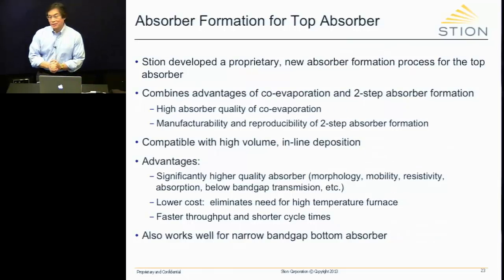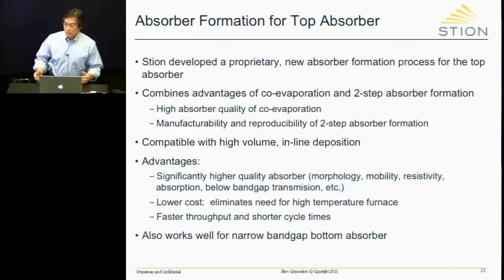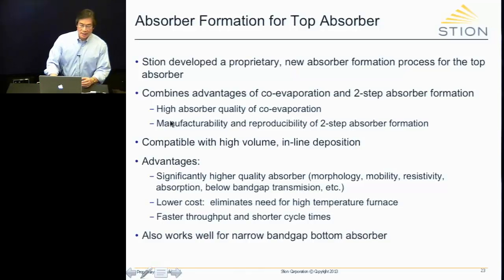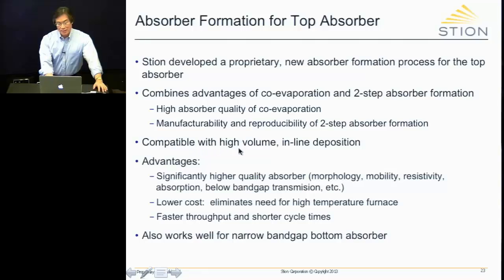At this stage, I can't tell you exactly what it is, but I can tell you that we developed a proprietary absorber formation system which combines the advantages of co-evaporation and the two-step absorber formation process that we just described. What it has is essentially the high absorber quality from co-evaporation and the manufacturability, reproducibility, and reliability of two-step absorber formation. Later I'll show you the SEM of the absorber, and you can judge for yourself how well that turns out. What's also very useful from a manufacturing perspective is that it's compatible with high-volume inline deposition. Okay. So this is what we're using for the top device.